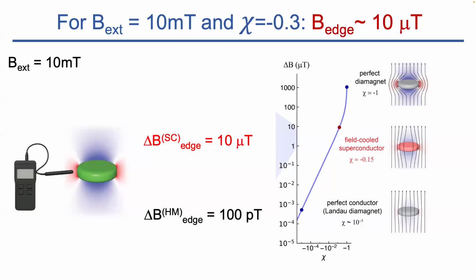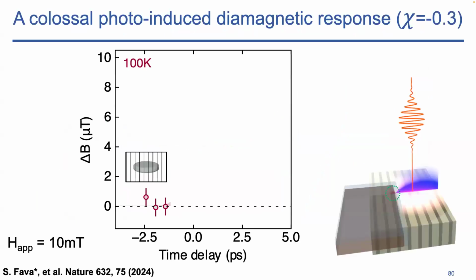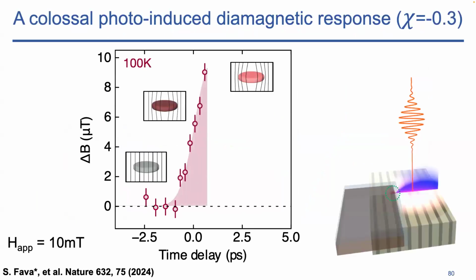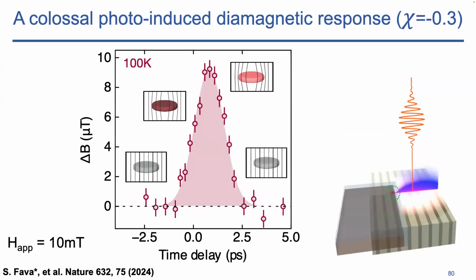And so now I'm going to do the experiment. We're going to pump this guy and use the fast Gauss meter here. And if I'm good, I'll measure 10 microtesla here on the edge. I start above TC, I photoexcite, and I want to see the field lines being expelled by my photoexcited state. So there you go. You pump it, this is now at 100 Kelvin, 2 times above TC. And what you find is that the magnetic field measured on the edge goes all the way to approximately 10 microtesla, which in a static picture, if you believe in magnetostatics, should be equivalent to a quench of the susceptibility from 10 to the minus 6 to minus 30%. So such a diamagnetic state in equilibrium can only come from a superconductor.